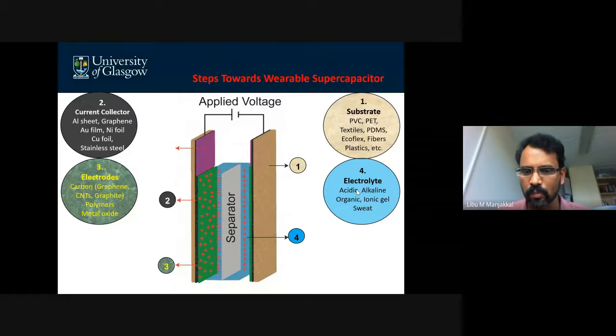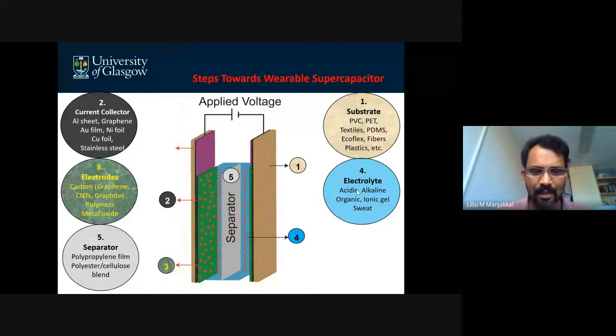This electrolyte choice depends fully on your operating potential. For example, if you are taking a water-based electrolyte like alkaline, sodium chloride, or KCl-based electrolyte, the water dissociation potential is almost 1.3 volt. So the maximum voltage you can operate is approximately 1 volt to get full operation. But if you need high operating voltage devices like 2.5 volt or 3 volt, you need an organic type of electrolyte or a different type of electrolyte. So depending on the type of your application, you can choose your electrolyte. And then you need a separator.